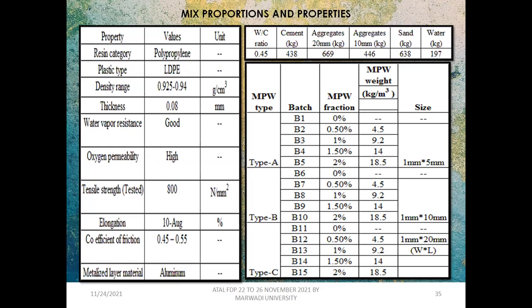These are the properties on the right-hand side. You can see the common properties of the metallized plastic. Then how we carried out the mix design: this is one example of the mixtures we utilized, and we maintained the water-cement ratio at 0.45. We tried a variety of fibers like fiber A, B, and C, with sizes varying in length. We varied the aspect ratio in that way.